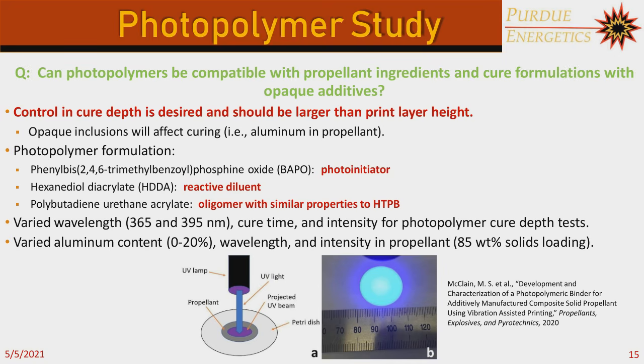The test that we designed was relatively simple. Down in the bottom, you can see that we have a region of uncured propellant pressed into a central circle on a petri dish. Then we shine a UV light onto that uncured propellant for 45 seconds. Once we turn the light off, we remove the cured propellant from the uncured propellant, and then we measure the thickness or depth of that cure. For the formulations, we kept the solids loading the same, at 85%, and what we varied was the intensity that we cured at, the wavelength, and the aluminum content.